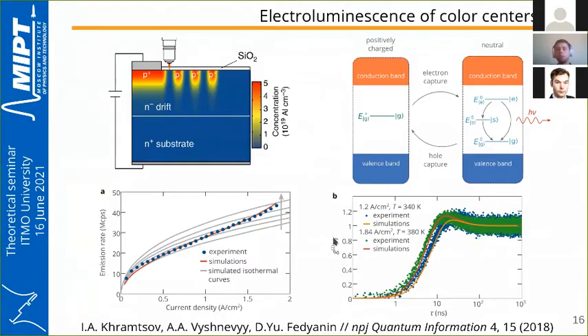But for the color center in silicon carbide, there was an article - actually only one article on single-photon sources in silicon carbide. The authors of this article provided us all the information we needed to perform the simulation. In this case, we were able to reproduce not only G2 functions at different currents, but also the dependence of the single-photon electroluminescence rate on the current density. Moreover, we predicted a self-heating effect that was later confirmed by the authors of this experimental paper.